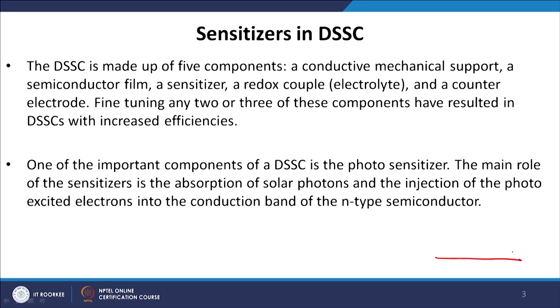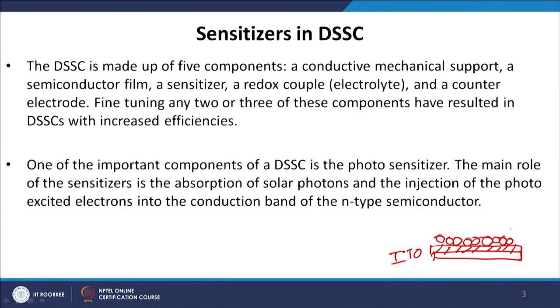The first component is the conductive mechanical support. In the last class we used indium tin oxide (ITO) coated glass substrate. The second is the semiconductor film — we used titanium dioxide, depositing a layer of TiO2 on top of the ITO substrate. Third is the sensitizer or dye molecule, whose role is to absorb sunlight. We dipped the TiO2 photoanode in a sensitizer solution — in the last class we used porphyrin as the sensitizer, and we can also use laser dyes or other sensitizer molecules. The dye molecule goes into the pores of the semiconductor and adsorbs on its surface.